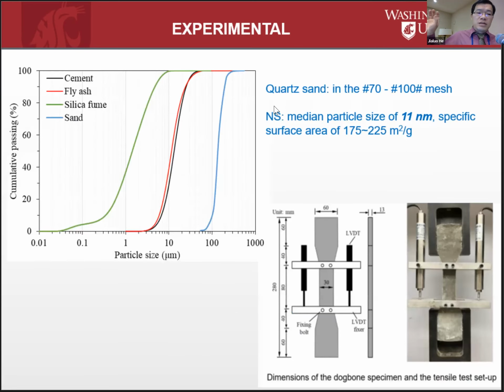Now, you can see the size gradation of some of these solid constituents like the cement, the ash, the silica fume, the sand. But actually on that chart, there's nowhere you can find the nanosilica because that would be at the very left side, because we're talking about less than 100 nanometer, which is less than 0.1 micron. So it's the very end of that curve. So we used a uniaxial tension test to evaluate the tensile performance of the PECC.